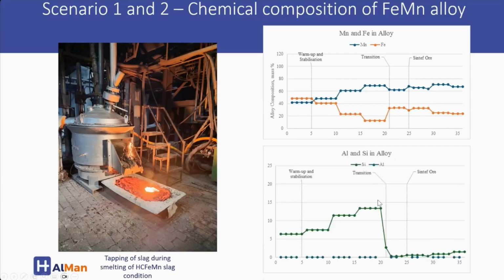So what happened? We can look at the impurities. With increasing aluminum addition, we also saw that you introduce more silicon into your alloy, and that's why aluminum is also diluting the grade of the manganese. You can see that clear distinction when you transition to sinter ore: your impurities and your alloy system change completely, and silicon is no longer that much of a problem as an impurity. But because we had to add much more aluminium to get to that lower manganese, you can start to see silicon actually coming up as an impurity as well.